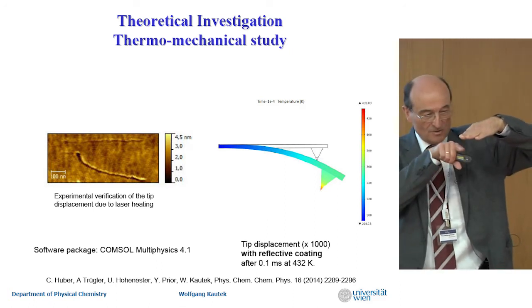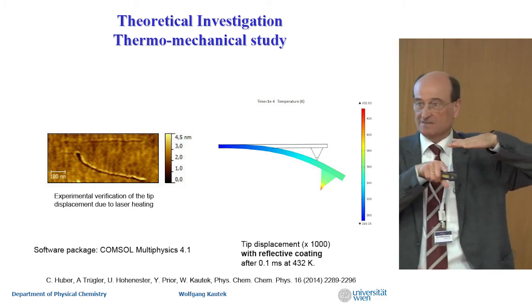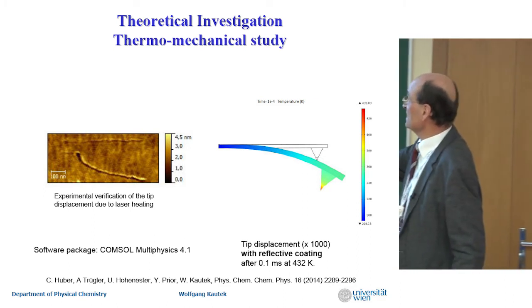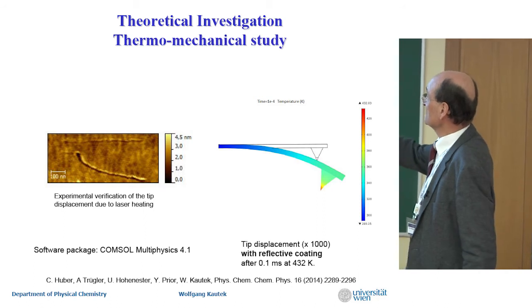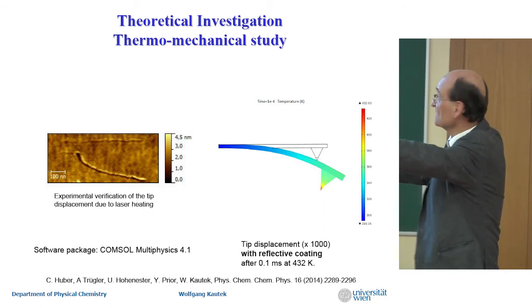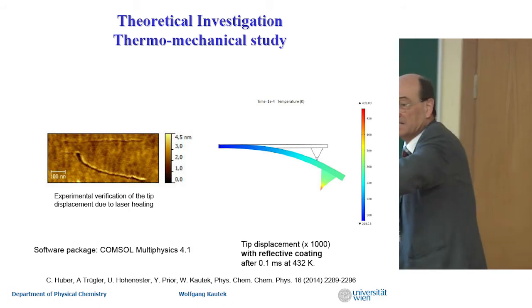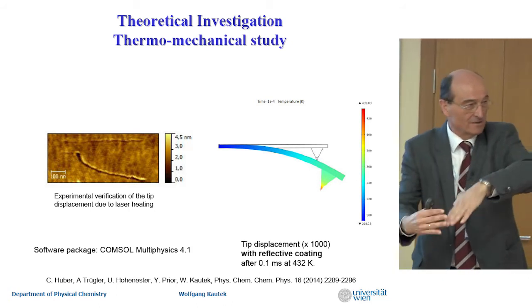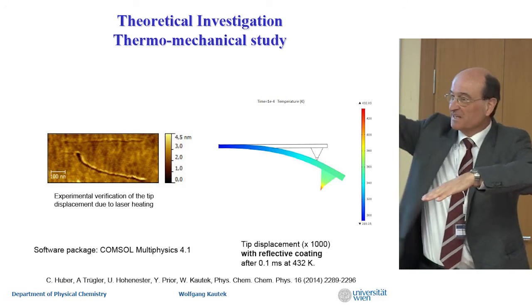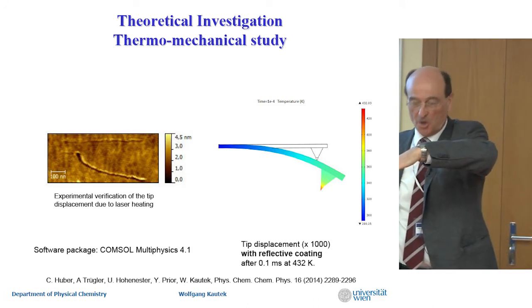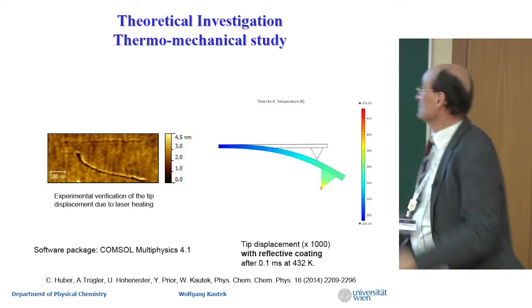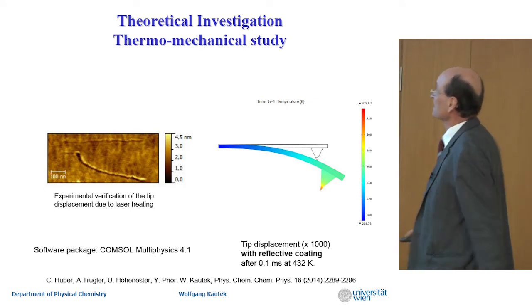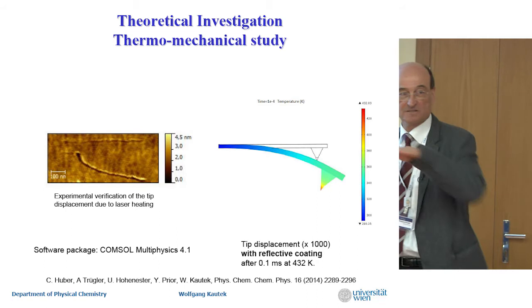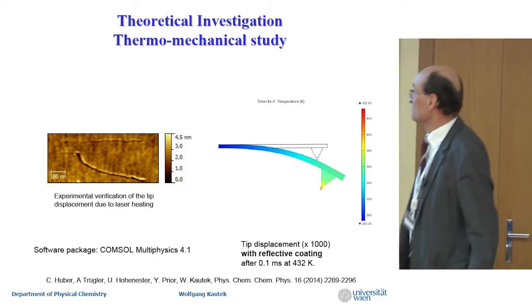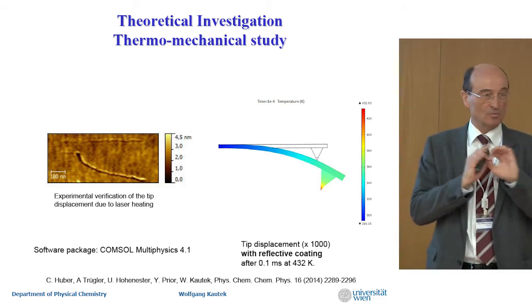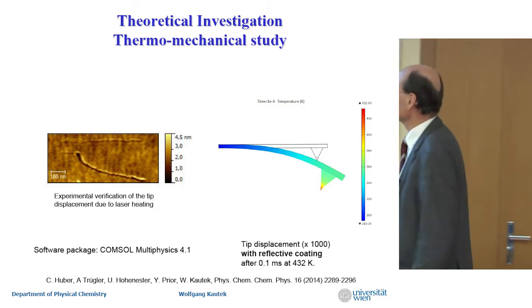Okay, now, such a cantilever is a fragile thing. You can imagine if you heat the tip, at the end everything is heat. It will dissipate the heat, and it will extend in one direction, the cantilever of the atomic force, and it will also bend down because there is a metal mirror on the back for the reflection of the laser light, for positioning, you know. So it will do this, and we were calculating and showed that it's the case, and actually we could also show an experiment. It does like this. So importantly, if you want to avoid that, you have to work at thermal equilibrium.